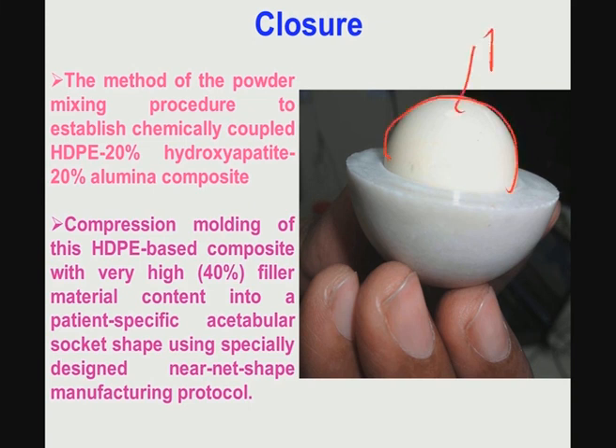Now, this is your alumina femoral head. Somebody is holding this alumina femoral head with the acetabular socket just to show how geometrical conformity can be established in this process. The alumina femoral head goes exactly inside and fits into the acetabular socket. In the process we have also established the fabrication route, how to fabricate this. Although I have not shown it, when we did microcomputer tomography of the ultra HDPE based socket, we noticed a uniform distribution of hydroxyapatite and alumina, and that it is a crack free and pore free composite. So, this process is also capable of producing structurally robust device components.